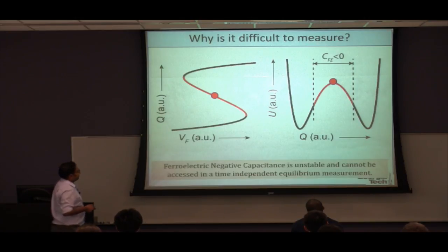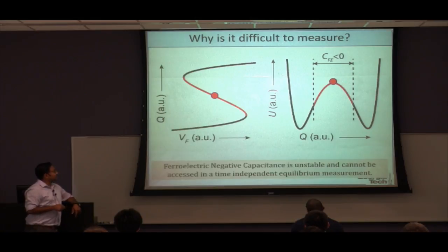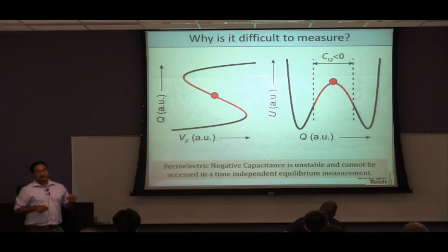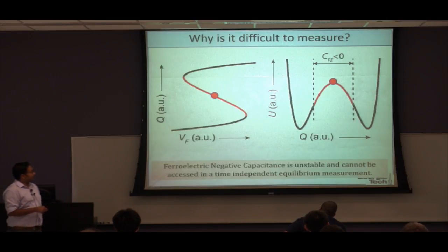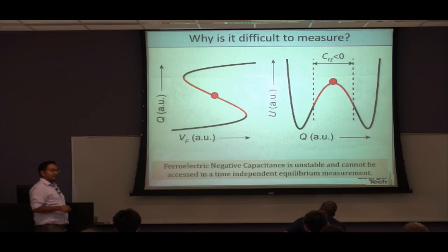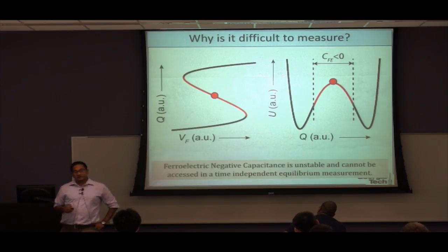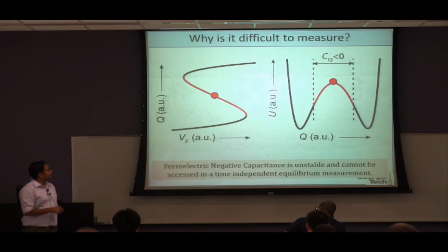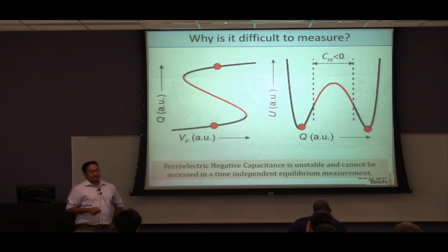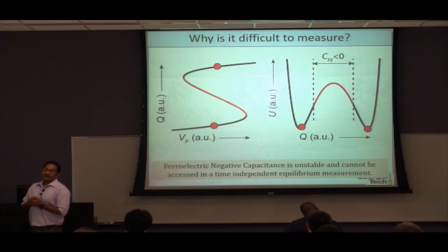And the reason is very simple. What we have said is that the capacitance is negative in this region, in red. And as you can readily see, this is actually not an energy-favored position, meaning that it is on top of a barrier. If you want to put the polarization on top of this barrier, it will automatically fall down to the nearest minima because it's an energy-unfavored state. So this essentially means that negative capacitance is an unstable state of the material.